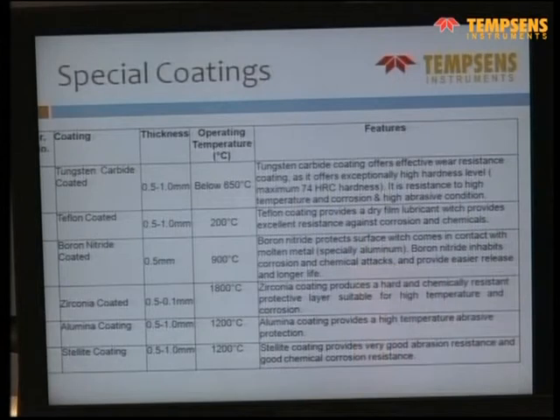There are some coatings available. Some of them we have listed here, like tungsten carbide coating. It gives a hard face onto the thermowell, which can offer a hardness up to 74 HRC. Then Teflon coating for chemical applications up to 200 degrees centigrade. Boron nitride coating for applications in molten aluminum, because boron nitride is a kind of lubricant, so the molten aluminum will not stick to the metal.